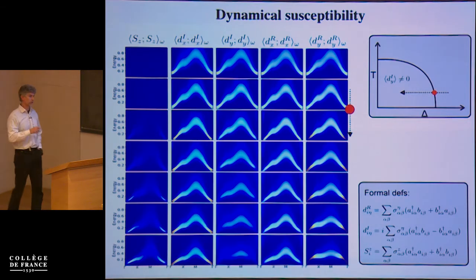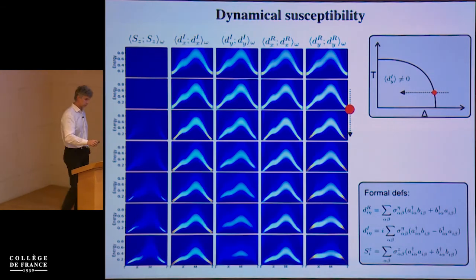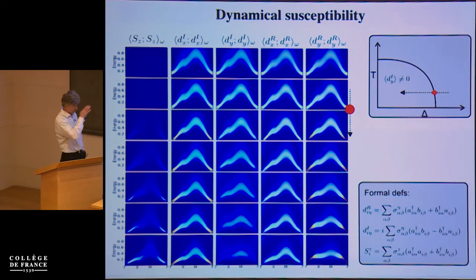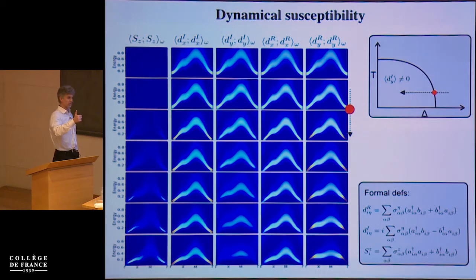That's right. What we are looking at in these calculations is a Hubbard model with a density-density interaction. So the continuous symmetry—we don't have SU(2) spin symmetry, we have only U(1), but this U(1) is broken because we have an order parameter which lies in-plane. So this is the continuous symmetry that is broken.